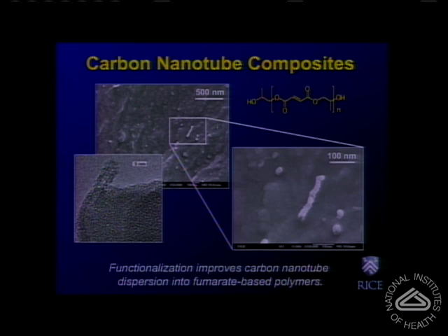The biggest challenge in fabricating these nanocomposites has been the nanodispersion of the nanomaterials within the bulk of the polymer matrix. For this reason, we and others have developed chemistries to functionalize the surface of the nanomaterials, in this particular case, the carbon nanotubes, to prevent their aggregation and to facilitate their nanodispersion within a polymerizing polymer matrix.